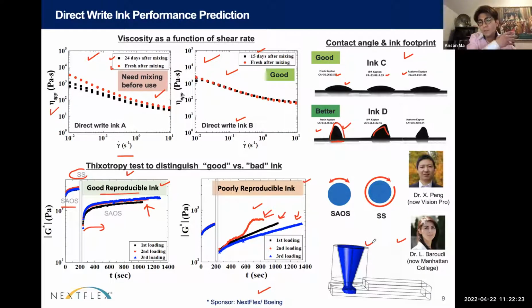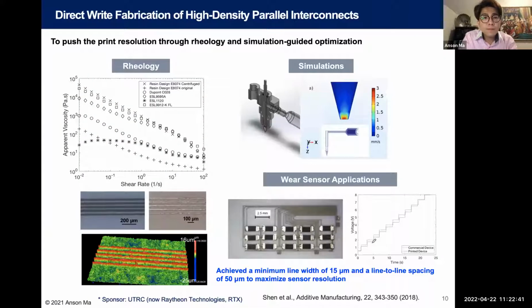And again, you can also run some simulations, try to understand how the ink rheology would impact the footprint of the line, and also how the processing conditions, like how fast you're dragging the nozzle and how fast you're pumping the material, would influence the print line resolution. And so this is also the student carrying on that work. And this is the tool that we use for the direct ink writing. And then you can do different rheology measurements for the materials. These are some commercial materials, and some we took the commercial material and did some modification to it. This work has already been published, but the idea back then was to create very high resolution lines.